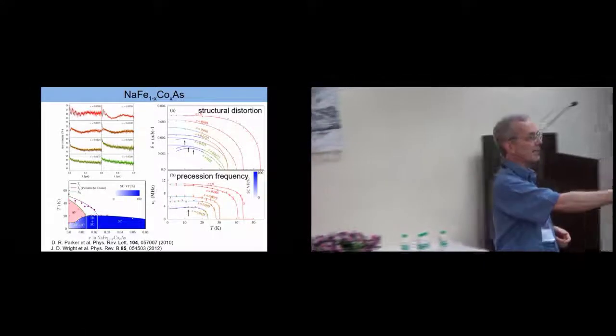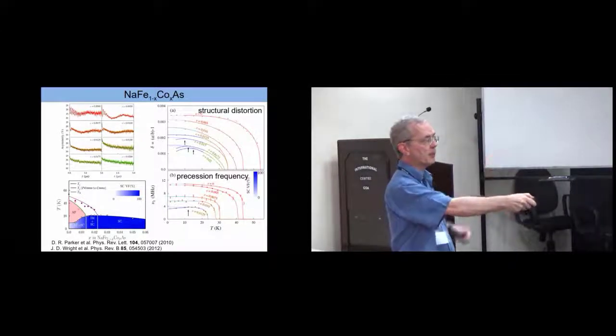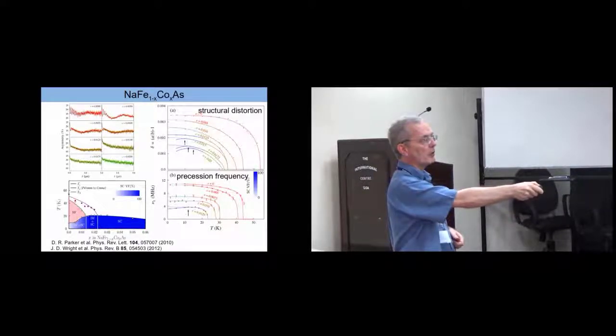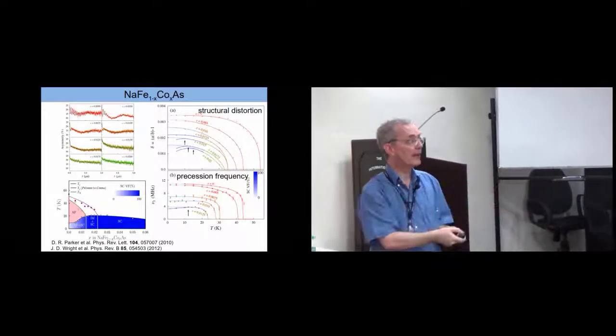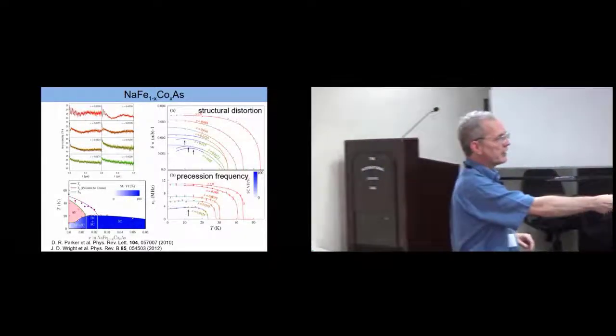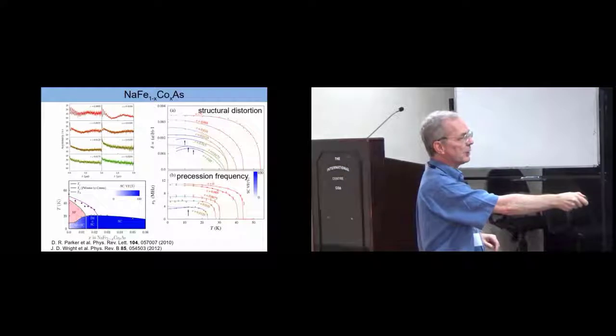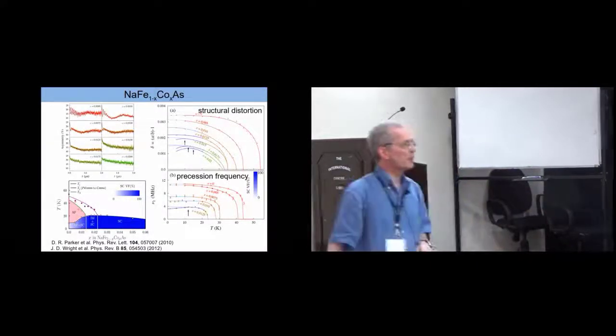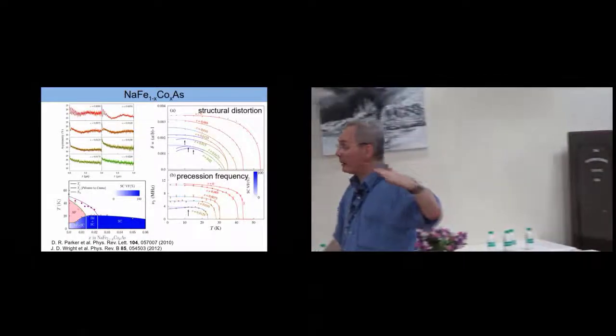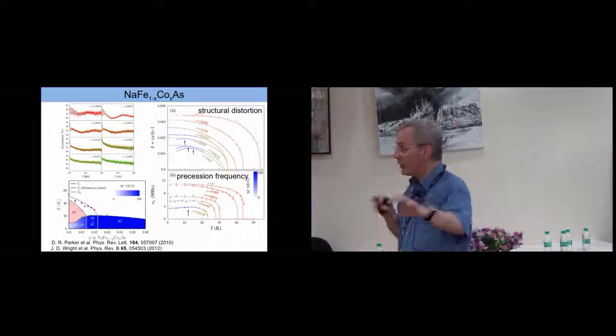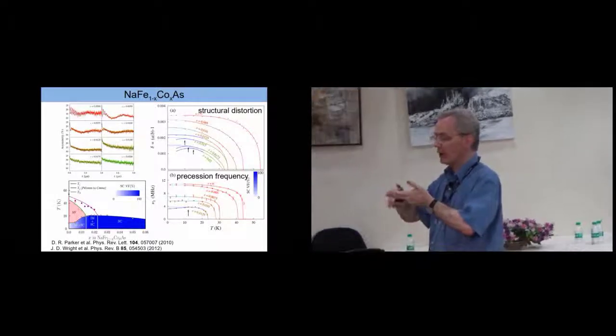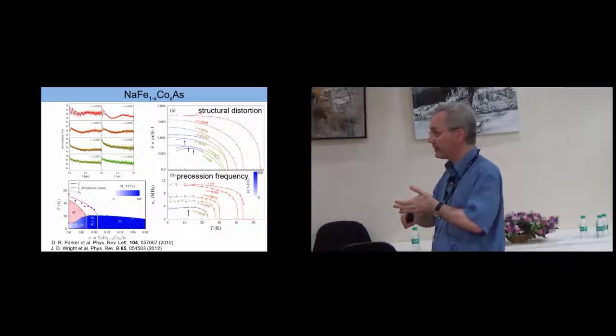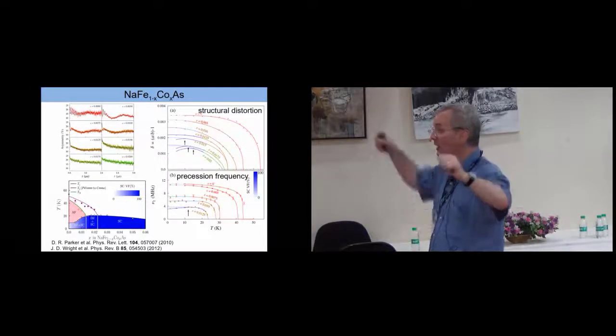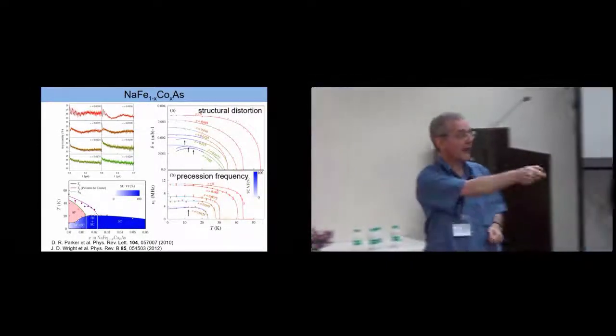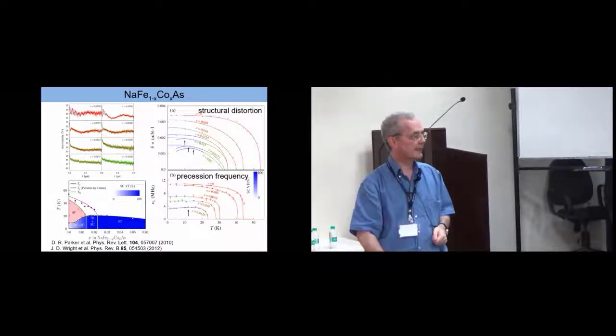But the other interesting thing is, as you dope more, which is what induces the superconductivity, the magnetic transition goes down, as does the structural transition, even with very small amounts of cobalt doping. And the other interesting thing is, when superconductivity sets in, which is when these curves go blue, which we've done to show the superconductivity, the order parameters actually go in the wrong direction. And so what you have is a competition between the structural, superconducting, and magnetic order parameters. When superconductivity turns on, the others get weaker. And this is a very nice thing to be able to probe using these techniques.